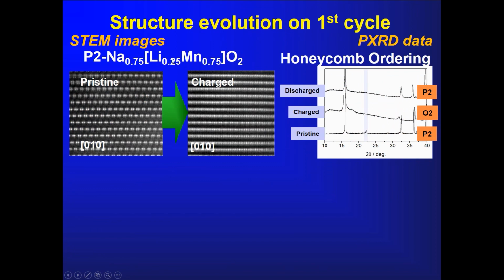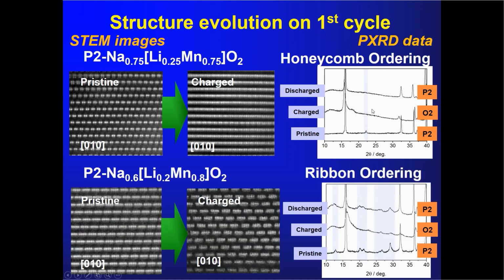So if you look at the 0.25 compound, I'll go through this one quite quickly because it's got the same features we saw in the lithium compounds. Here's the pristine material, the dumbbells. You get the same disordering on charge. You're losing the honeycomb arrangement. There is an extra complication here that you go from a P2 to an O2 stacking, but the point is it's never recovered again. It's the irreversible process that you saw.